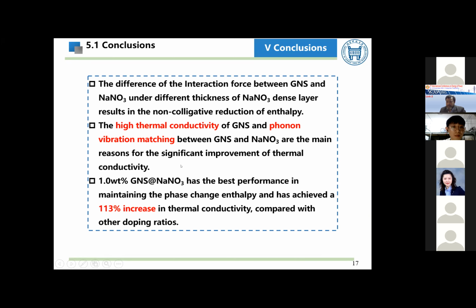And the 1% doping ratio has the best performance in maintaining the phase change enthalpy and has achieved a 113% increase in thermal conductivity compared with other doping ratios.